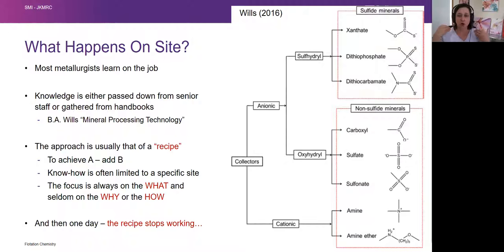Would exact mineral chemistry — for example, trace element substitutions or variation of iron in siderite — be important for flotation? Would an EPMA analysis be important? Yes, absolutely. Particularly for minerals such as pyrite, the microchemistry or nanochemistry can have a very disproportionate effect on surface properties. The surface properties of pyrite are very strongly determined by its electrochemistry and its electrochemical rest potential. The tiniest variations in its internal geochemistry — such as the presence of different trace elements within its matrix — can have a very disproportionate effect on its electrochemical potential and hence the way it reacts in solution.